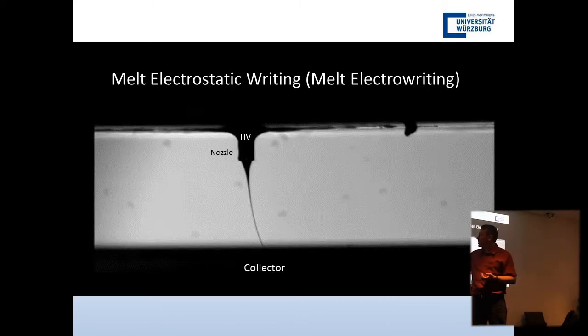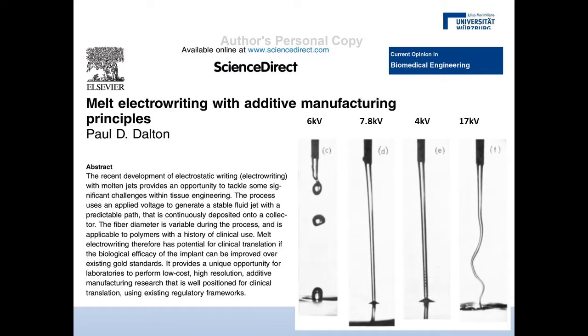Here we have a video. We have basically a fluid that's falling. And if we didn't have this voltage, this jet would break up. Yeah? And what happens is when you apply a voltage, you can actually stabilize this falling fluid at a low flow rate. This is an example, also from Dalton's paper, where at 6 kV you're still getting droplet breakup. You reach a threshold where suddenly you get this contiguous jet. Once you've achieved that, you can now drop down the voltage down to 4 kV. Here you're starting to get some droplet breakup. So the use of a voltage in our systems isn't to eject a jet like an electrospin, but it's there to prevent these kind of instabilities just before the droplet breakup.